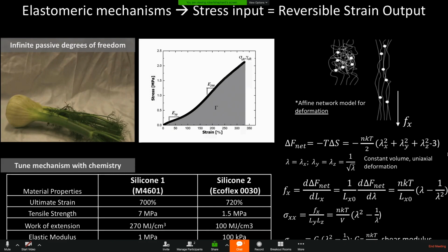When you're engineering soft robots for embodied intelligence, you can think about designing with toughness instead of strength. So the strength is the maximum stress before the material yields, which is pretty low relative to, say, steel. But the energy absorbed, it depends, but can be large, especially when you consider the strain to failure. And if you were to push a piece of steel an inch, it would stay in that condition. But if you were to push a slab of rubber an inch, it would come back.